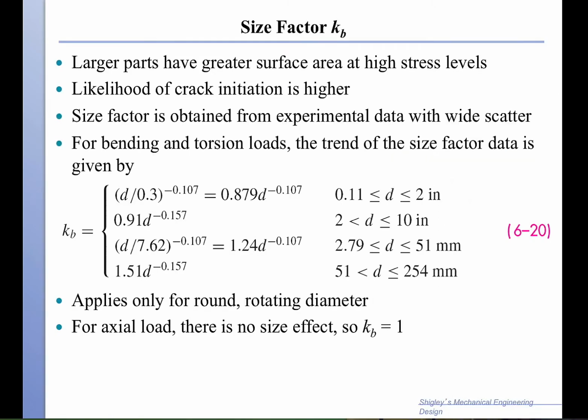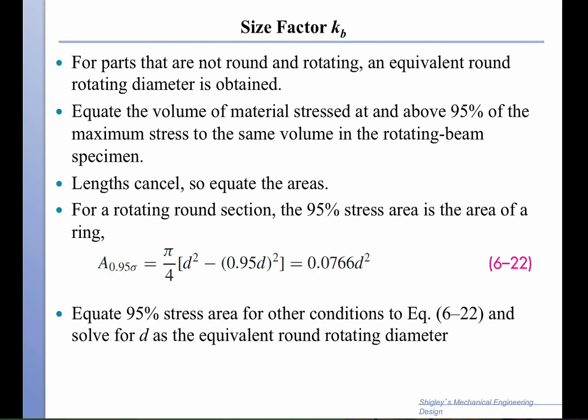Now, if we look at the size factor, as we mentioned, it is the ratio of the diameter by 0.3 inches raised to the power 0.107. For larger sizes, you get 0.91 times d to the minus 0.157, and this is all in inches. If you have millimeters, then you use these factors. Next is the size factor for cross sections that are not round and rotating.